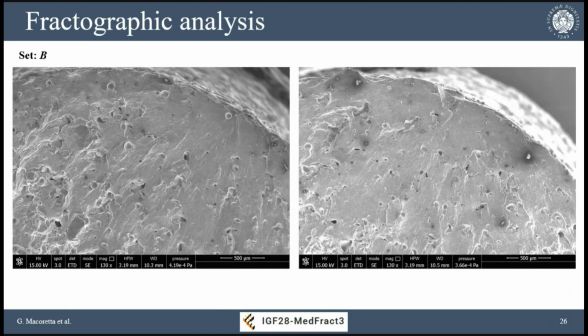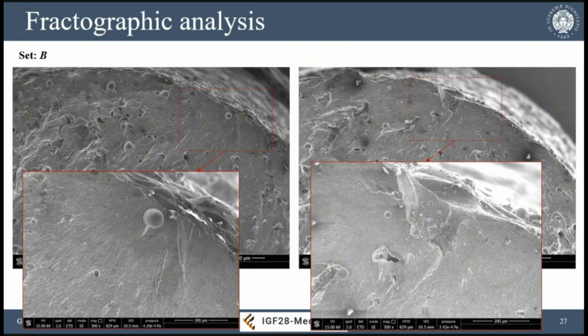What happens with the B process parameter set? The crack onset was on the surface, as for the A set, in regions with surface roughness valleys or defects - very deep valleys that occur due to local melt pool instability on the surface, and also some bigger pores nearby the surface. These act as killer defects and are much more severe than in the A set.